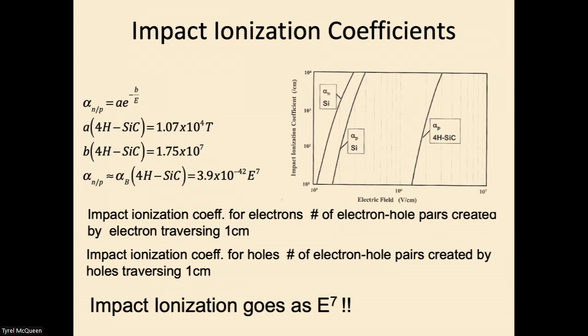So this process of impact ionization is characterized by the impact ionization coefficients, which are represented by the Chynoweth equations in terms of an A and B parameter. These coefficients are very, very sensitive to the electric field, and they are really a function of the material. You can see the impact ionization coefficients for silicon, and here, vastly different, are those for silicon carbide.